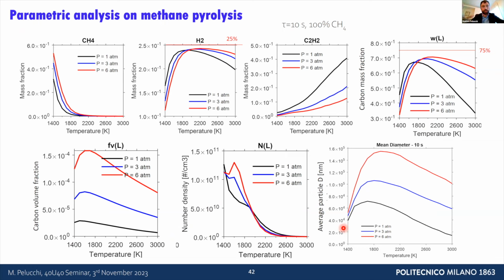In other words, we're trying to close the material balance, the carbon balance, which is probably not easy to close experimentally. At least the model can provide some closure to this carbon balance. So we can look and make predictions based on the pressure effect, temperature effect, residence time effect. We can look at all of the different intermediates. Acetylene has an important role in turquoise hydrogen production, and also some safety related issues—acetylene is quite explosive. Acetylene pyrolysis is exothermic.